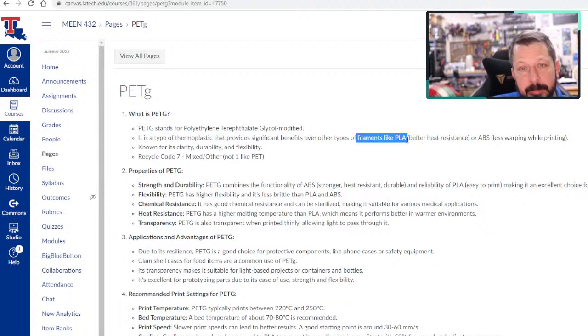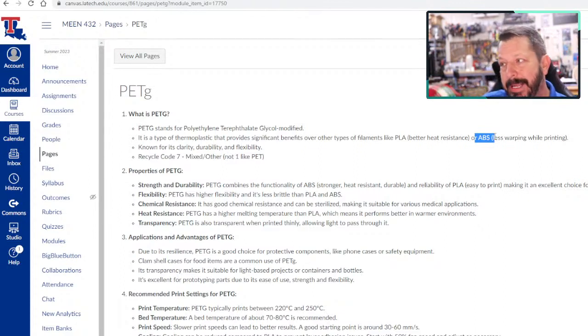It does have some benefits over PLA. For instance, it's not particularly more difficult to print than PLA, but it has a higher heat resistance. So the glass transition temperature of PLA is in the 60 to 65 Celsius range. PETg is closer to 80 Celsius. So that's a pretty significant bump in how hot PETg can get before it starts to deform. And it's a little bit easier to print than ABS. So ABS does have an even higher glass transition temperature, but ABS has some issues with warping. It smells bad. It usually has to be in an enclosure to print it. So it's just got some issues on printing with this kind of printer.